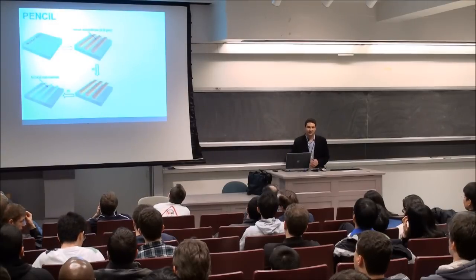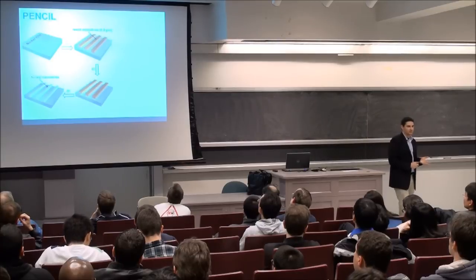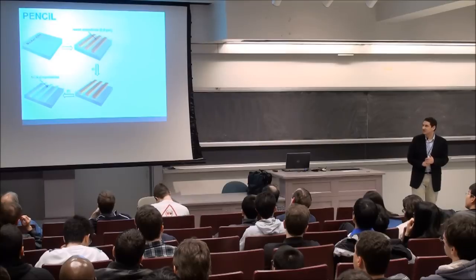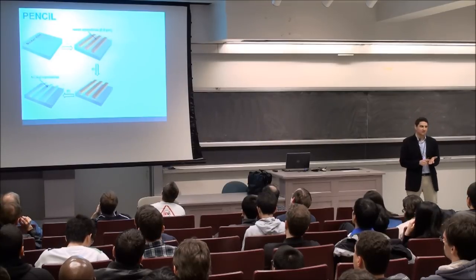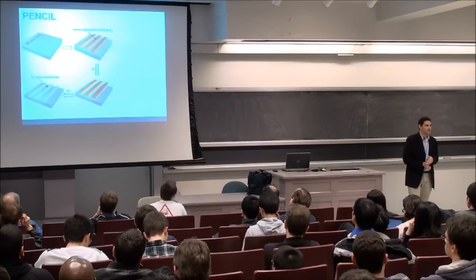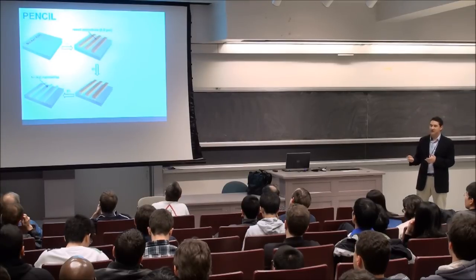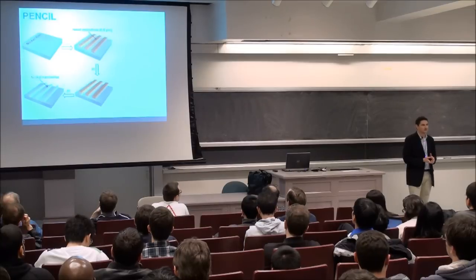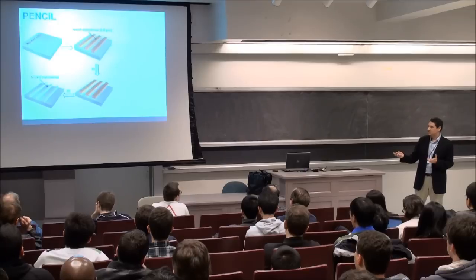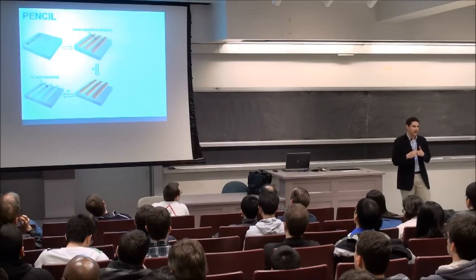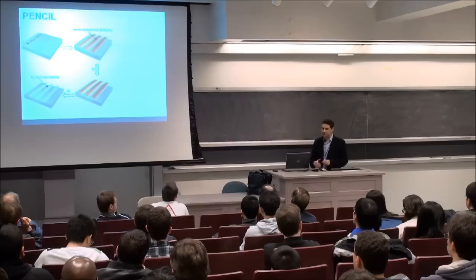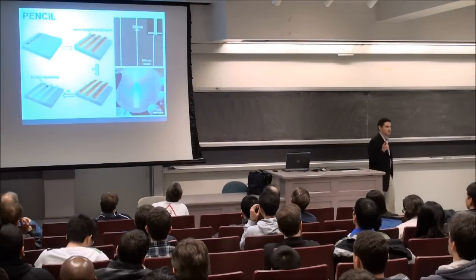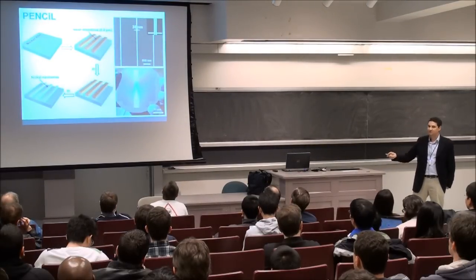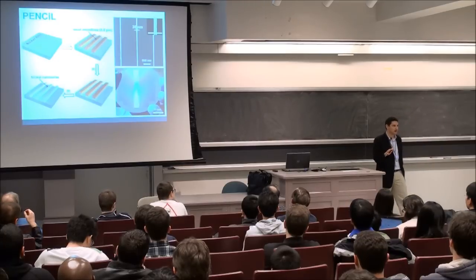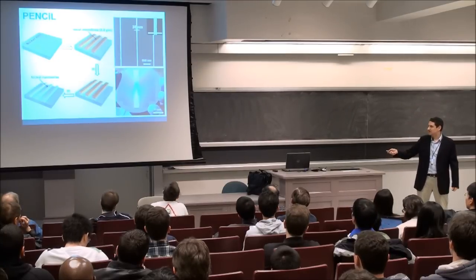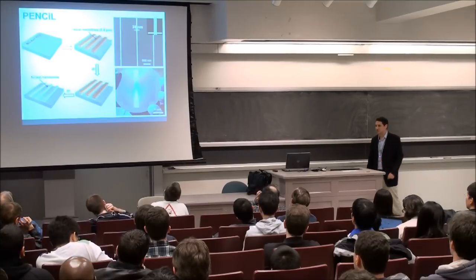And we can also pattern the graphene in interesting ways in order to make a nanoscale material and then to see what the binding looks like. So we developed this approach which we call photolithography and etching for nanoscale lithography that we call pencil, because all these things need some sort of acronym. And basically the way this works is you just coat a wafer with nickel, and then you do standard microlithography on that wafer, and you undercut etch the nickel. And actually you can etch it down to pretty significantly small features. For example, here's nickel that we patterned down to like the 30 nanometer level using this pencil approach. And of course, since the photolithography is the base of this approach, you can do it over an entire wafer. So if you hold the wafer up to sunlight, you'll actually diffract the natural sunlight there. You can see it with these nanowires patterned over the whole wafer.